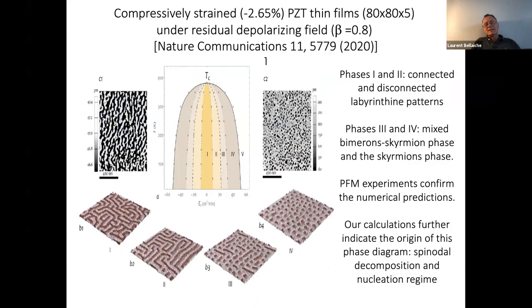And a lot of things that we did over the years, but let me go over a recent paper. It's a Nature Communications paper done by Yousra Nahas and Sergei Prokhorenko and our collaborators in Australia from the group of Professor Valanoor. And this is a temperature versus electric field phase diagram. And this temperature is the temperature at which you quench the system from high temperature to this special temperature. And this phase diagram is very interesting because it tells you you can have a lot of different phases depending on your quench temperature, depending on the electric field that you put into the system.